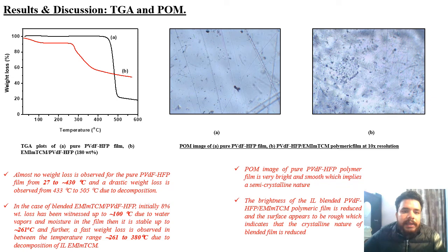Here you can see the TGA and POM micrographs. In the TGA graph, in case of pure PVDF-HFP, the copolymer is stable until 430 degrees Celsius, and then a drastic weight loss occurs till 505 degrees Celsius, which is due to the decomposition of the copolymer. After that, at 600 degrees Celsius, almost 20% of the PVDF-HFP is remaining.